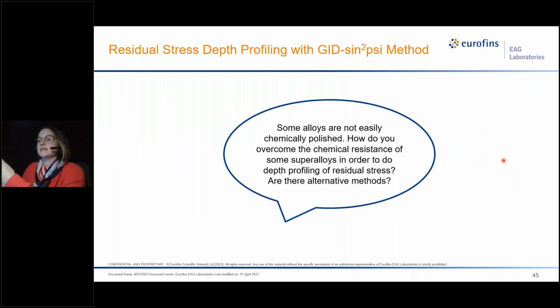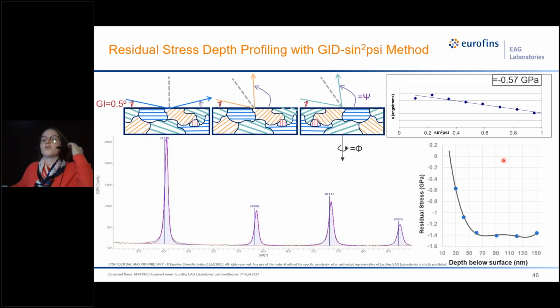Now, the next question that came in: some alloys are not easily chemically polished. How do you overcome chemical resistance of some superalloys in order to do depth profiling of residual stress? Are there alternative methods? Yes. By chemically polishing, I'm assuming what this person meant was that we're applying some kind of chemical to strip a layer, then do residual stress, rinse, repeat. We don't actually need to do that if we're using the grazing incidence sine squared psi method. In grazing incidence, remember, we have a fixed incident angle and we're rotating and moving our detector. So in this case, the detector's here.